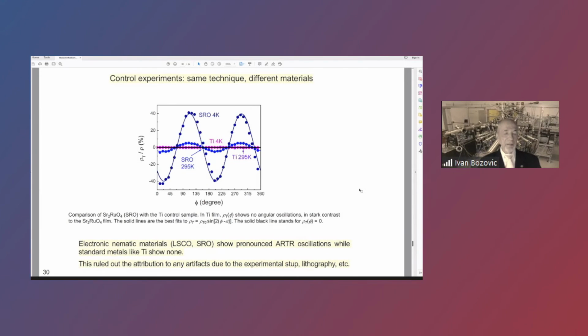And finally, as another logical check, we perform the same type of measurement using the same mask on other materials, quite a few. What is shown here are two, strontium ruthenate and titanium. Strontium ruthenate is, like cuprates, a strange metal, strongly correlated. And indeed, we have observed an even larger nematicity signal. This is Sr2RuO4, 214 structure.